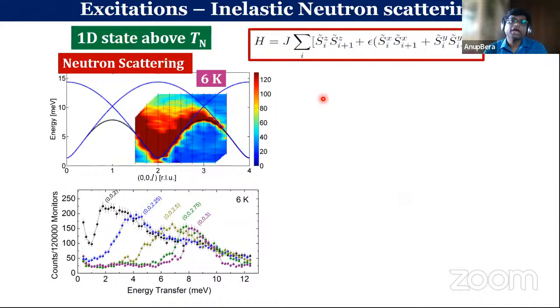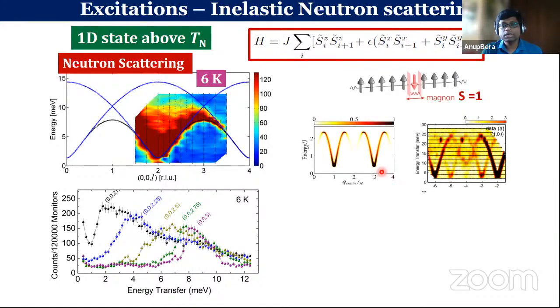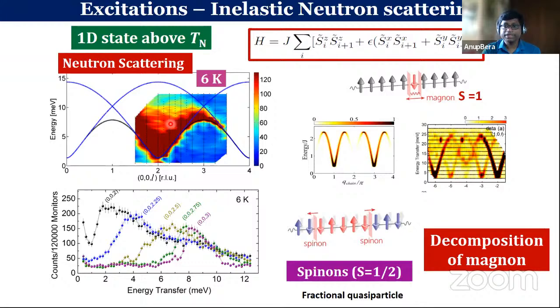Now, here I have shown the inelastic pattern, which shows a very broad and diffuse type of behavior, which is very much in contrast with the excitation for the previous compound based on nickel. In the nickel case, we know that magnetic excitations are magnons. They are spin 1 quasi-particles, and they have very well-defined dispersion relations. But we don't see that in the case of the cobalt compound, which is spin half. So what exactly is happening here?